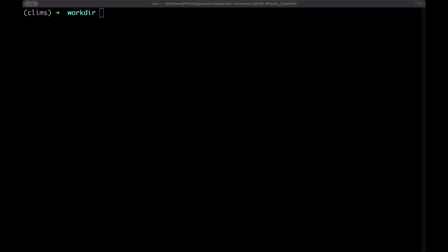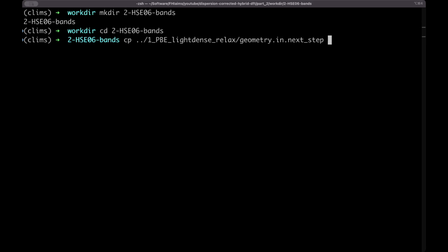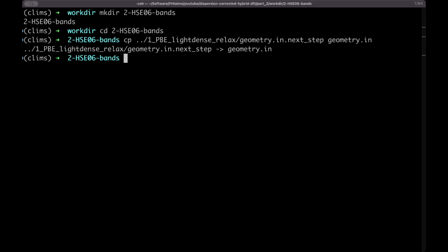As a next step, we will perform the density of states calculation and band structure calculations with Mulliken charge analysis. To accurately compute the band structure of the system, HSE06 has been proven to be a good choice in terms of reasonably balancing costs as well as accuracy. This system here contains heavy atoms, so it is important to also use an advanced relativistic scheme. Here, we will perform a hybrid functional calculation with HSE, with perturbative spin-orbit coupling for the eigenvalues. Let's take a look at how to set up such a calculation.